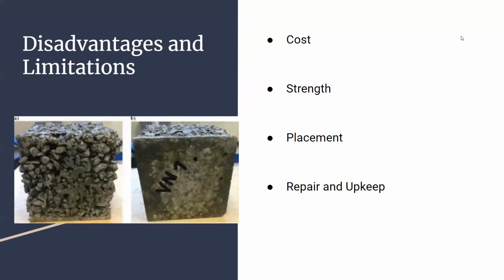The disadvantage of placement has to do with the difficulty of handling it since its workability is so bad. Its low water to cement ratio makes the mix very stiff, which allows the pores to form, but also increases the difficulty of placing the concrete. To make matters worse, the concrete has to be placed in a specific way, or else the characteristics of the concrete may change drastically. It also takes a longer time to cure than other concretes, which may be inconvenient in some settings. Fly ash is sometimes used to increase the workability of the concrete.